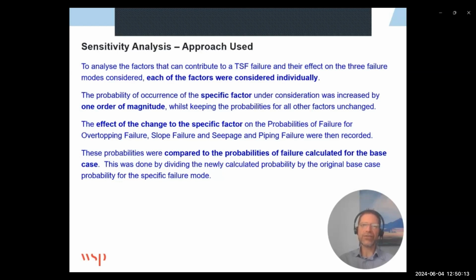The effect of the change to the specific factor on the probabilities of failure for overtopping failure, slope failure, and seepage and piping failure were then recorded. These probabilities were compared to the probabilities of failure calculated for the base case. This was done by dividing the newly calculated probability by the original base case probability for the specific failure mode.